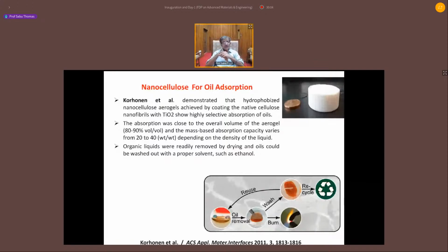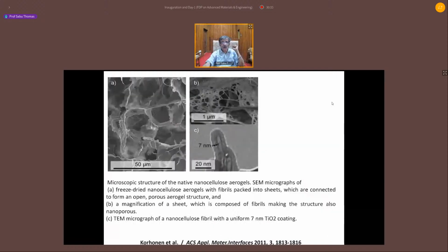You know what they did? They made nanocellulose aerogel. If you want to manufacture aerogel, it's a very simple process. You take nanocellulose and water and you go for a freeze-drying process. You can get aerogel. And then the group did something interesting. See, this aerogel is extremely hydrophilic because nanocellulose is hydrophilic. You know what they did? They gave a coating of titanium dioxide on the surface of nanocellulose. Look at this. Once you give the coating on the surface of nanocellulose, it becomes hydrophobic. And then you put it in water.